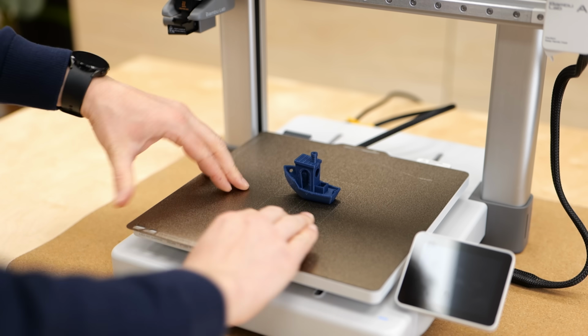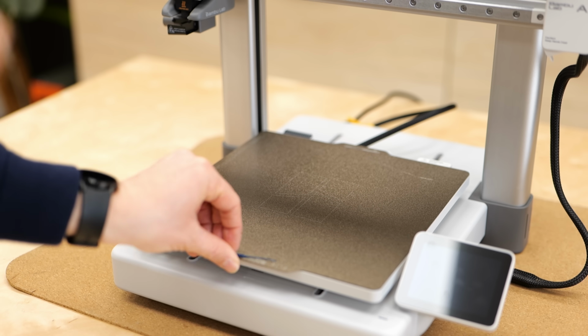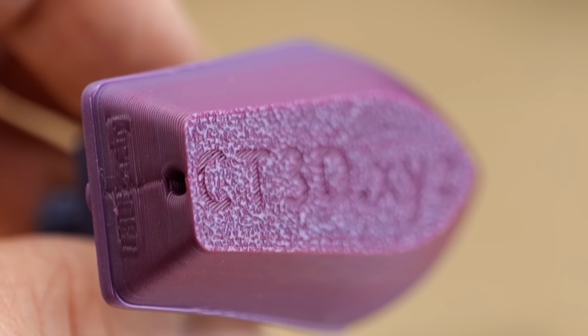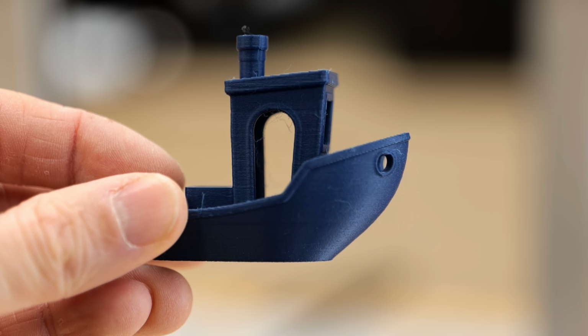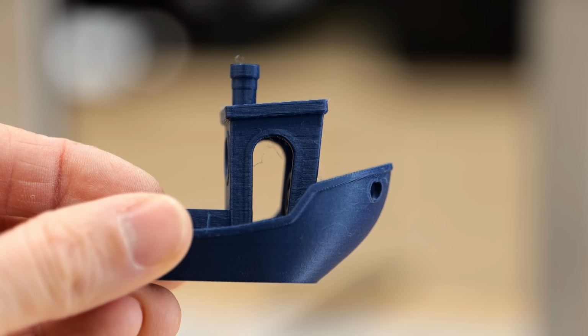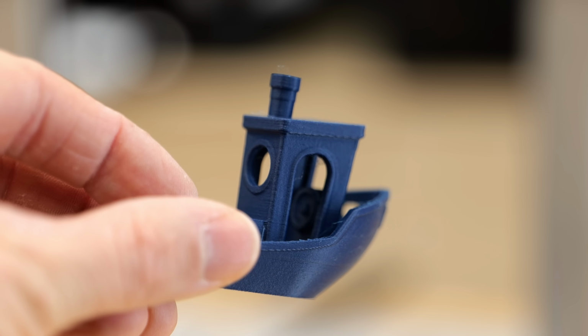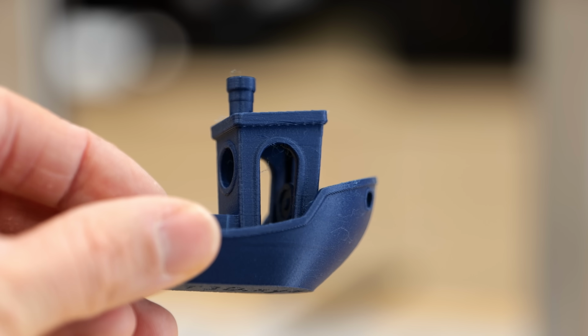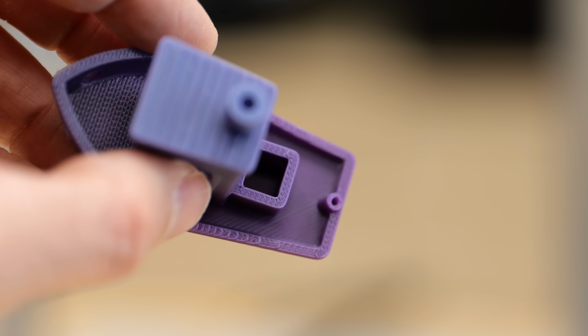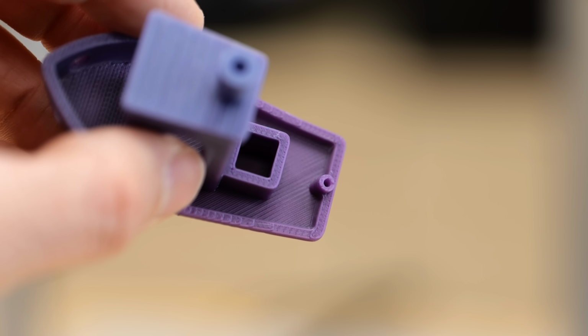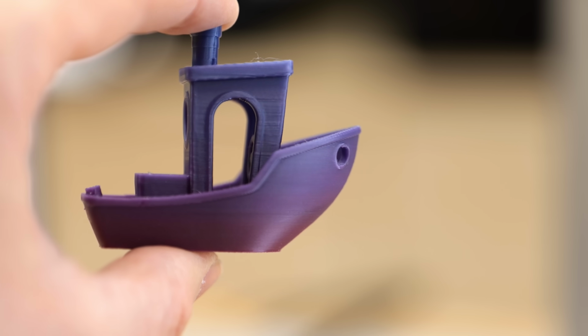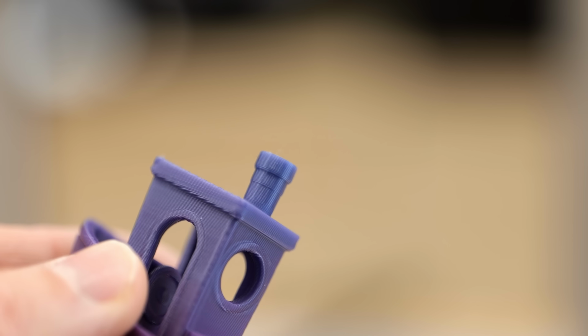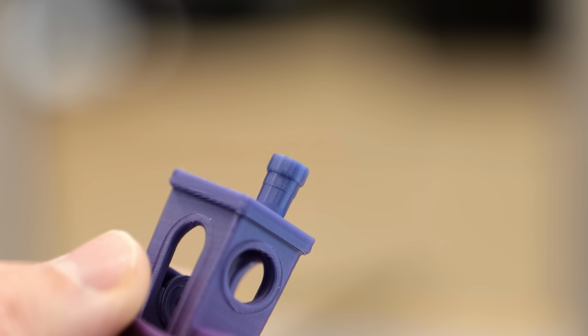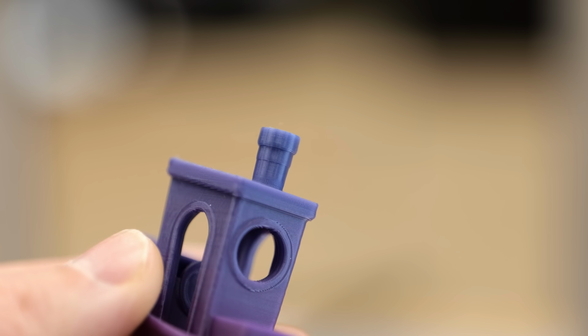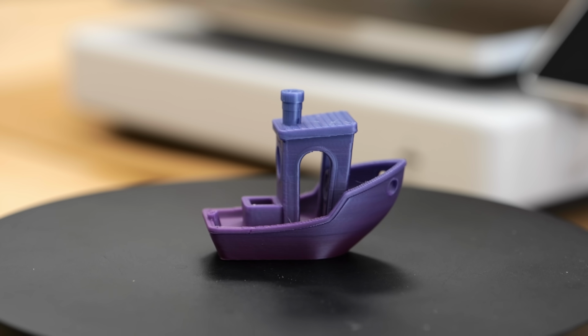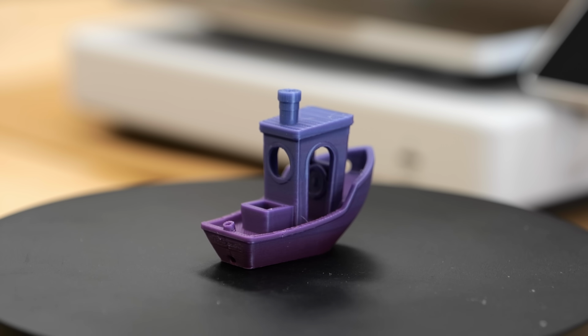You're not chasing perfection here, you're mainly looking for red flags. The first layer should be flat, with extrusion lines just barely visible. Look for stringing, which are these tiny little hairs all over the part that can indicate nozzle temperatures being too high or moist filament. Check top surfaces for holes and roughnesses, which indicate if material flow is too high or too low. Sidewalls should be smooth. And make sure that the bow and the chimney look good, because that can be an indicator of insufficient cooling. A modern printer should produce a Benchy that looks at least this good, if not even better.